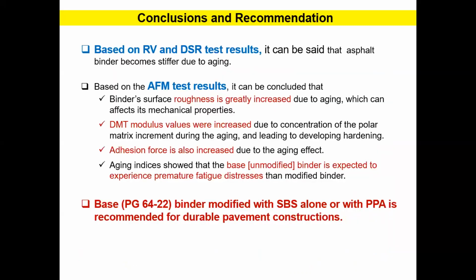So finally, based on the RV and DSR test results, it can be said that in case of asphalt binders, regardless of aging condition or binder types, asphalt binder becomes stiffer with the increment of aging, and the AFM result shows that the binder surface roughness significantly changes due to aging, which may affect its mechanical properties. Moreover, the DMT modulus values were significantly increased due to the increment of polar matrix concentration during aging that leads to asphalt hardening.